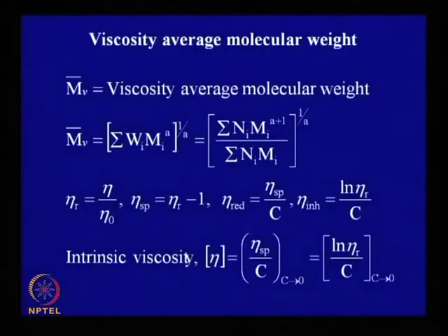So, here it is shown intrinsic viscosity, either you can go through specific viscosity divided by C as C tends to 0, meaning infinite dilution, or ln eta relative by C up to infinite dilution.